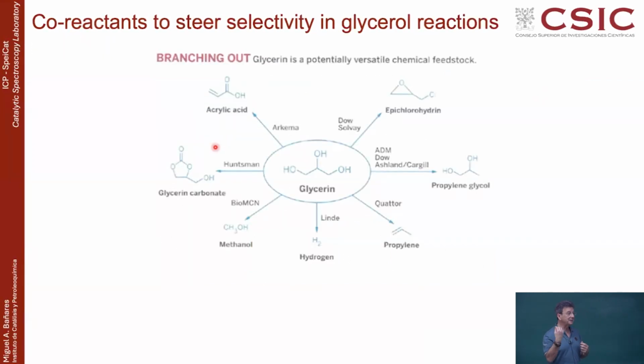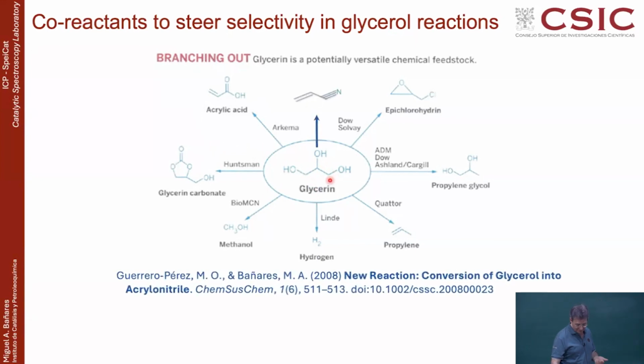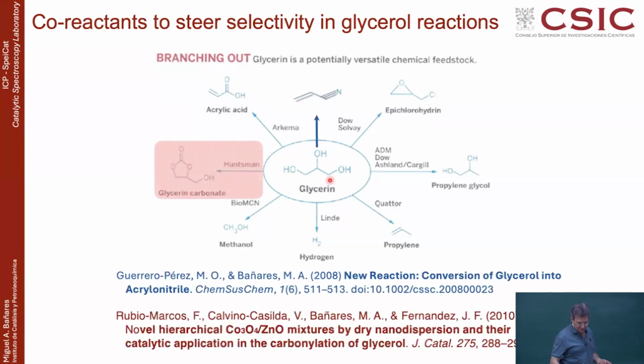So in the end, like I said before, you need a partner, a co-reactant to steer selectivity. Okay, you like many things, but here you have a Ferrari. Goes to the Ferrari. You need something. How do you do that? Well, there are many processes where they do that, adding different kinds of co-reactants to steer the selectivity. One of the processes that I like is the one to make glycerol carbonate. Basically, it's the reaction of glycerol with CO2. And then you will make a carbonate, which is basically this ring that you observe here. So you have the 3 carbons of glycerol, and then the carbonate binds to these 2 hydroxyls, making this.